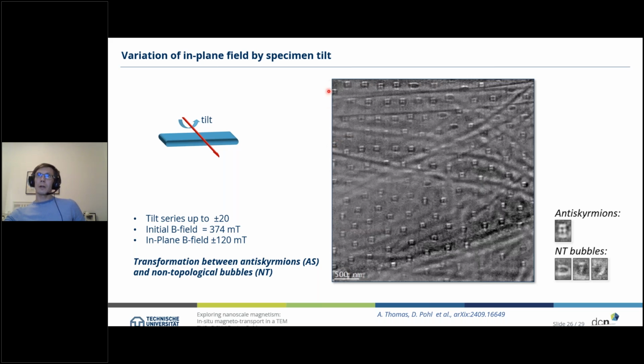So I want to run that tilt series now for you to give you a feeling about how the experiment was done. So you see, we start with a sample which has mainly anti-skyrmions. You see the square-like features. What you also see here are the bending contours due to the crystallinity of the sample. And of course, if we tilt the sample, you will see all these bending contours moving through the image area, which makes it a bit tricky to follow.